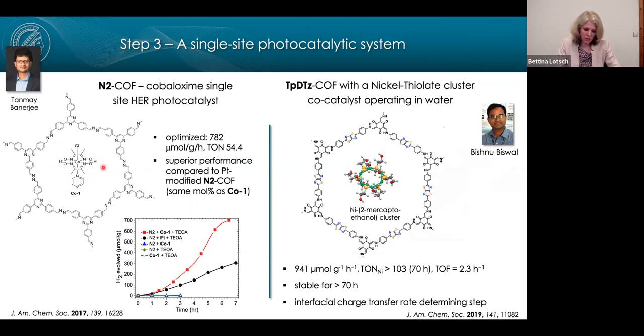And we simply put them into the suspension of the COF. And what we saw is that we see quite stable and continued hydrogen evolution with this cobaloxime catalyst that is actually more efficient than using platinum in the system. I should say, though, that we optimized, of course, for the cobaloxime. And this is actually a bit of a problem because the catalysis then only works in an acetonitrile water mixture of water 1 and not in pure water. And so that's something, of course, we wanted